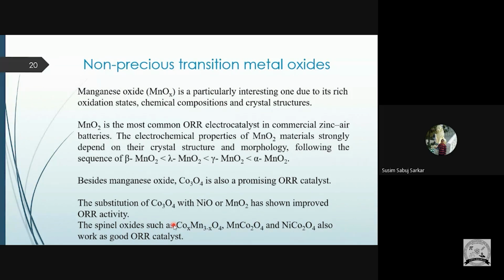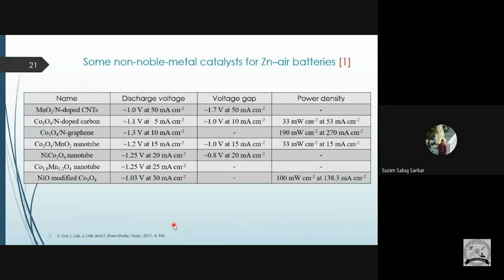This does not give that much of platinum, but we can use this at an affordable range. But the problem is, this is our discharge voltage. In that case, there is lots of MnO2 and N-doped CNT. It is given 50 milliampere current at 1 volt. If you see, this is increasing with time, that this is the Co3O4 gives 1.3, and the 10, well, current is very low, 10 milliampere.